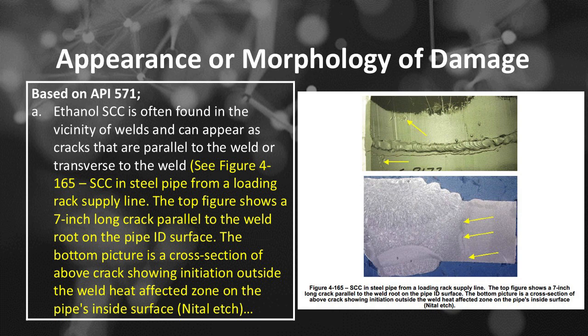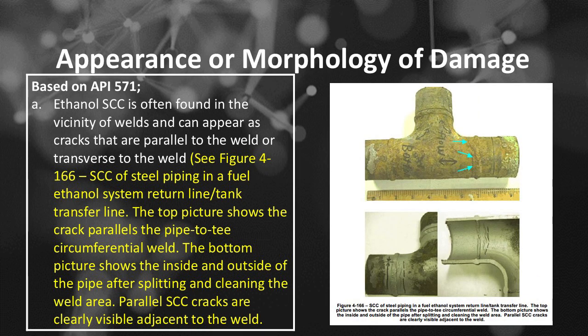See Figure 4-165, SCC in steel pipe from a loading rack supply line. The top figure shows a 7-inch long crack parallel to the weld root on the pipe ID surface. The bottom picture is a cross-section of the above crack showing initiation outside the weld heat affected zone on the pipe's inside surface, nital etch. See Figure 4-166, SCC of steel piping in a fuel ethanol system return line/tank transfer line. The top picture shows the crack parallels the pipe to T circumferential weld. The bottom picture shows the inside and outside of the pipe after splitting and cleaning the weld area. Parallel SCC cracks are clearly visible adjacent to the weld.